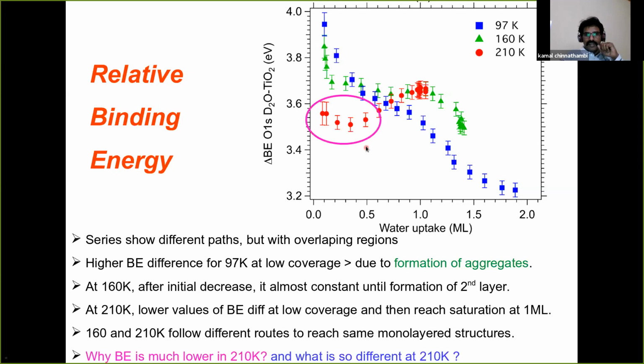Okay, this part I already mentioned. So we need to ask why it is so much lower. Before that, do you have any clue from the experiment why this particular case is different? If you remember the previous slide, the only major difference between the 210 degree and the other temperatures is that in this case we have a higher degree of dissociation for the 210 degree. So that may be one of the reasons. That's the information we got from the experiments that we are trying to use in our calculations.